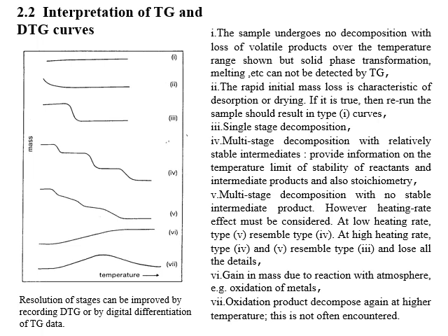Number 3 is an example of a single stage decomposition. So the calcium carbonate curves. CaCO3 decomposes into CaO and CO2. That would be a single step decomposition. The step function shown in number 4 is a multi-stage decomposition with relatively stable intermediates. So that basically means that there's not a lot of overlap of the various decomposition stages, and that between decomposition stages, the reactants are relatively stable.